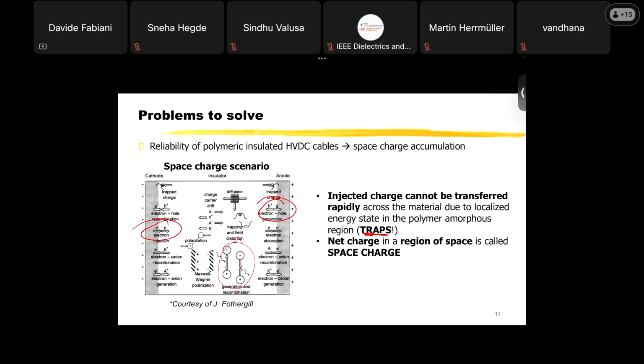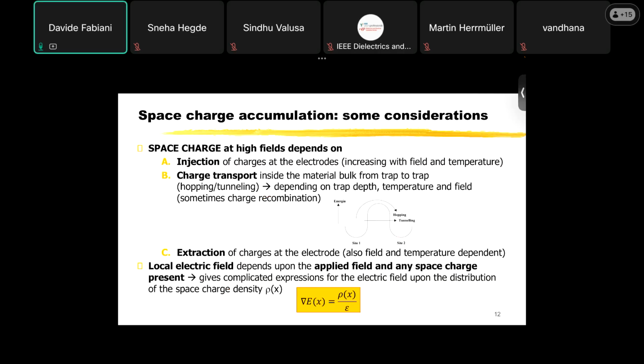This space charge becomes quite important at high fields because the injection of charge at the electrodes, the charge that we have seen here, the negative charge coming from the cathode, the positive charge coming from the anode, increases with the field and the temperature also. So increasing field and temperature, you can have a lot of charge that is injected in your material. We have then another mechanism, which is the charge transport inside the material bulk. And this charge transport occurs from one trap to another trap.